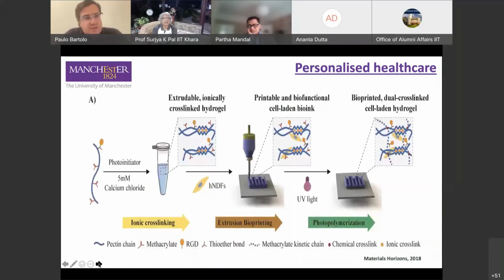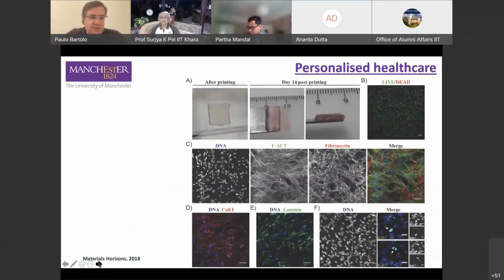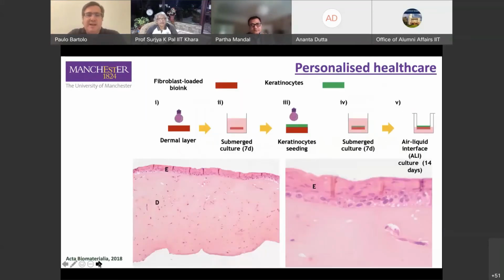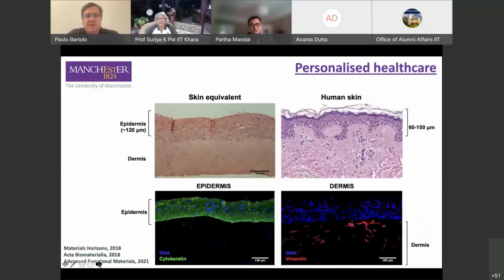We spent 3 years to develop our current bio-ink, and this is a pectin-based bio-ink printed through a dual cross-linking process. Initially, we perform an ionic cross-linking with calcium chloride to slightly increase the viscosity, guaranteeing a good printability. After printing, we irradiate using UV radiation to complete the polymerization process. We observed in the first trials that after 14 days, cells were alive, were able to create cell-cell networks and to produce their own matrix. And then we increased the complexity, creating a real skin construct. The results are illustrated here.